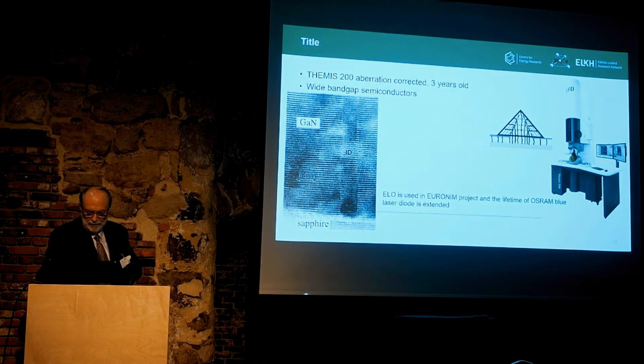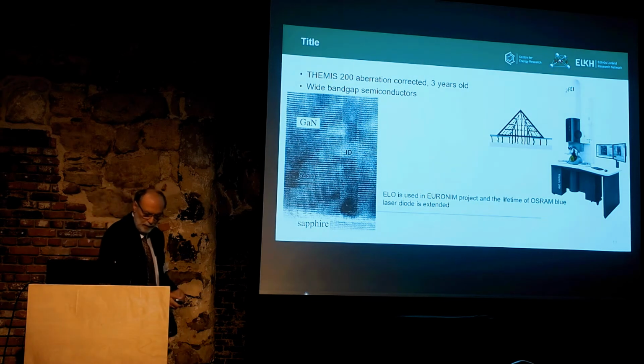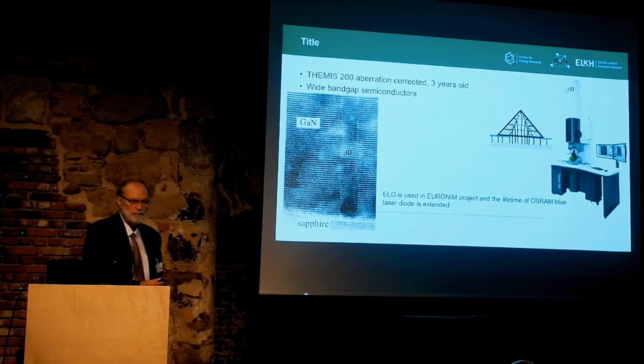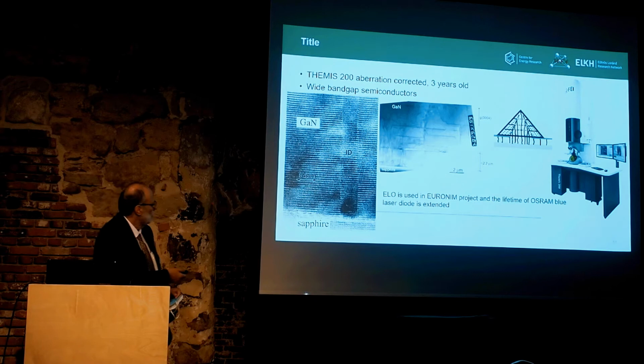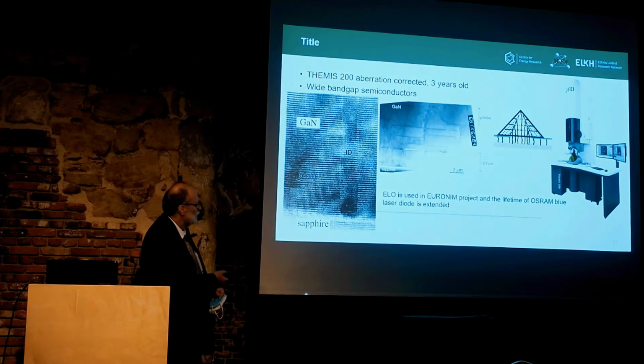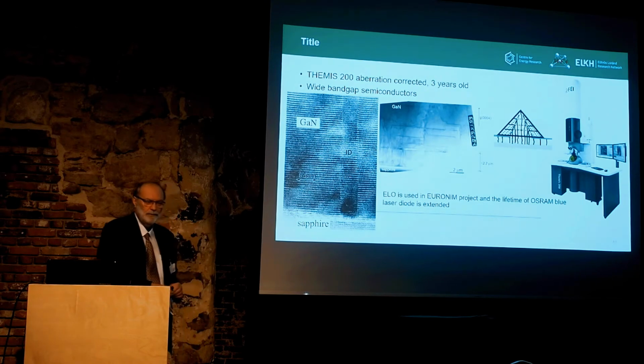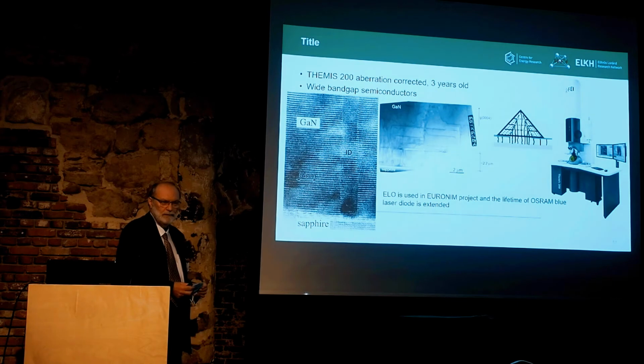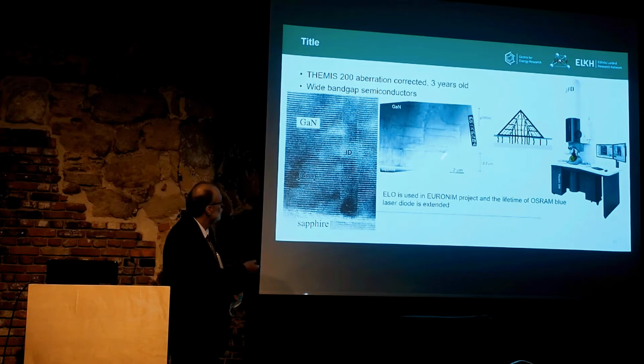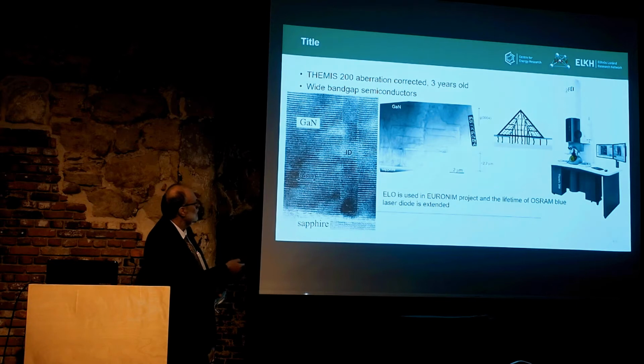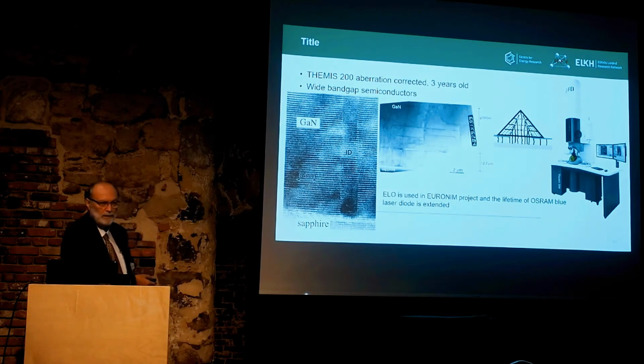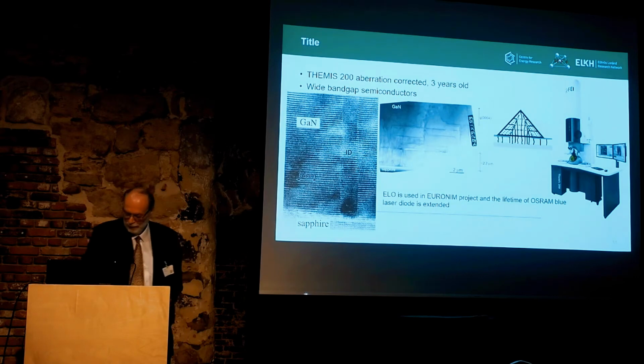My research going back 20 years was focused on gallium nitride and related materials, which is the material of the blue lasers. So we studied a lot of basic defects in gallium nitride in the 90s. Then I think in 2001, Osram published that they prepared the European blue laser diode, but they didn't publish that the lifetime was 1 minute. So then we had a European project, and with French partners we prepared this kind of structure in which the dislocation density in this very nice material was decreased, and the lifetime was increased first to 100 hours instead of 1 minute, and then further and further.